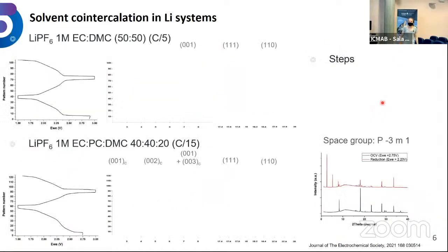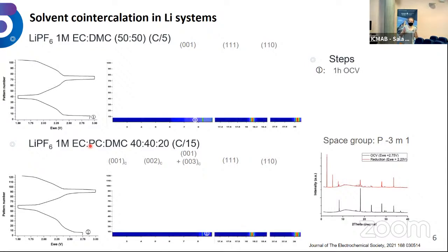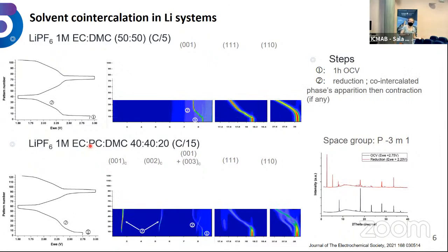Okay, let's dive into the results. So here I am comparing 2 cells. One with this electrolyte, which is a commercial electrolyte for lithium batteries. And here I have a different electrolyte where I added a little bit of propylene carbonate into the solvent mix. So let's compare both results. The first step of my cycling was to do nothing. I just collected a few patterns to make sure there was no spontaneous evolution. Then I start reducing the cell. In the first cell,